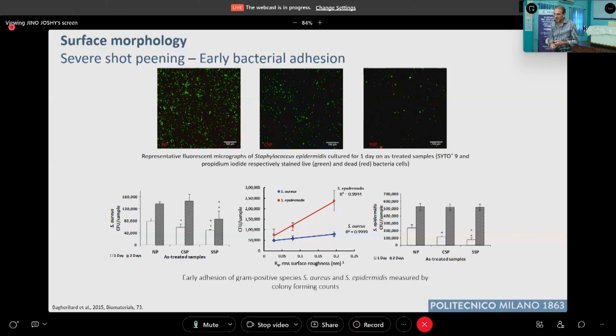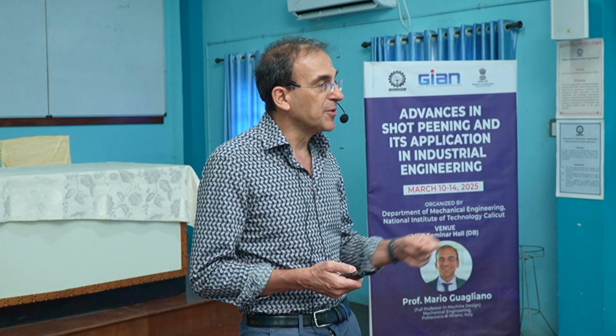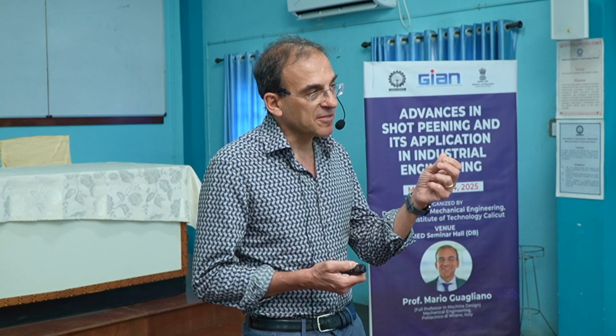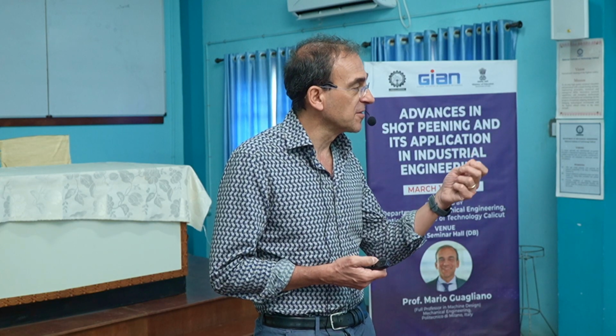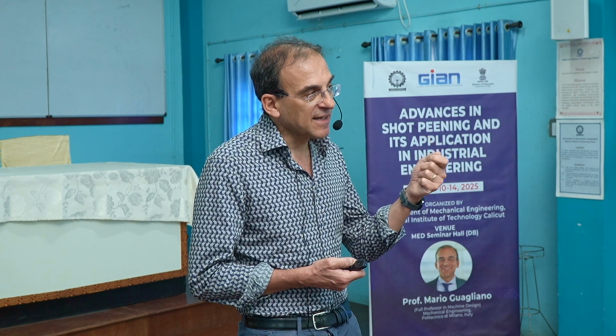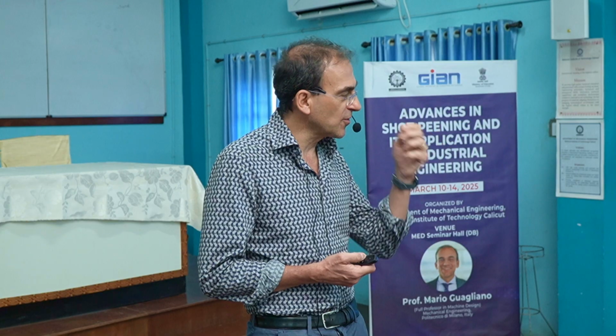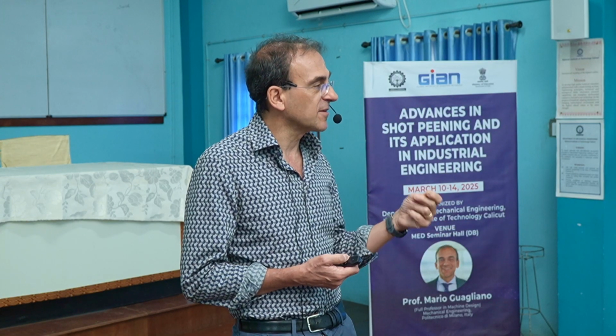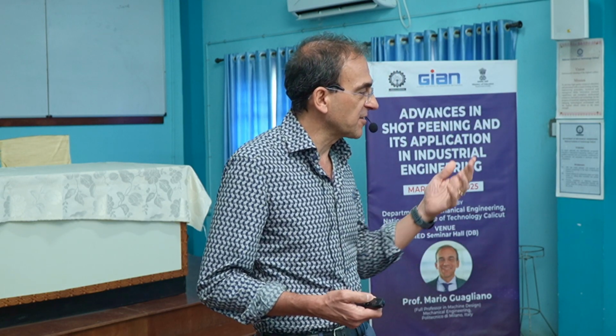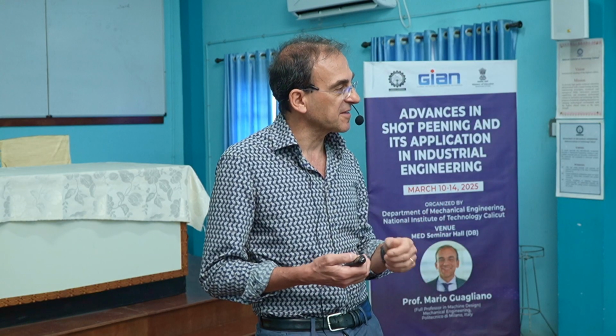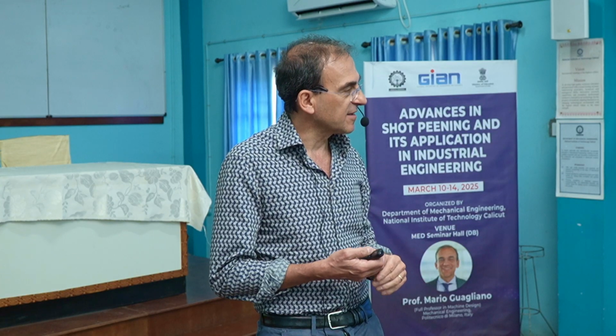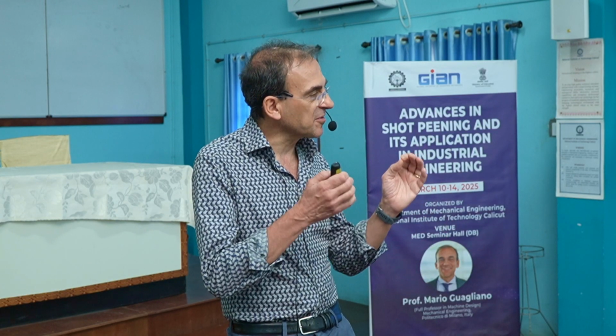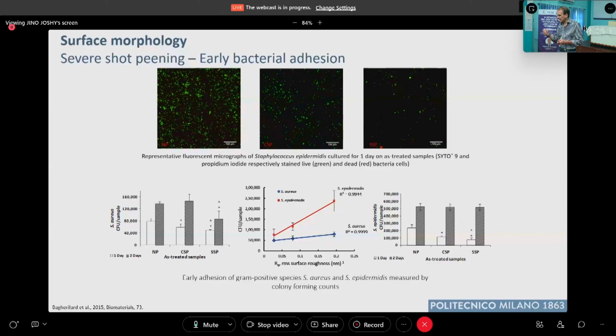We also, this is not shown here, have performed similar tests on pure iron. Why? Because pure iron is compatible with the human body and is also biodegradable. The aim at that time was to use shot peening to control the biodegradation rate in the human body of possible devices, rivets and so on, that can be used in orthopedics for fixing broken bones. And in the end, also in this case, it's possible to tune the biodegradation rate of this part by using shot peening. And this was also interesting. If you are interested, I can send you the paper we wrote about that.